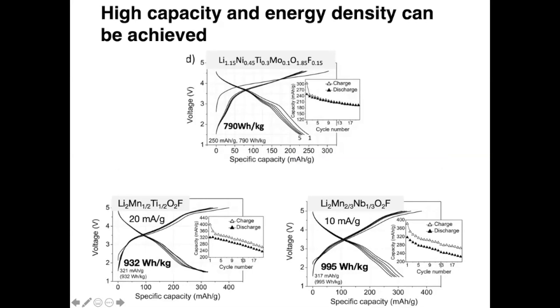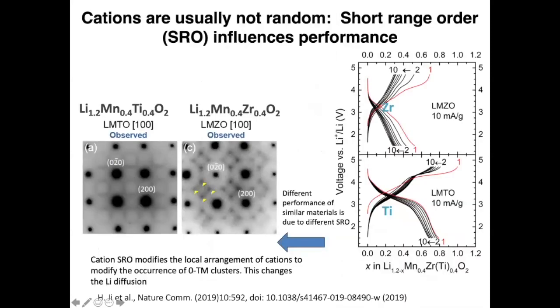You can, in general, get quite high capacity. A lot of these materials hit 700, 800, even approaching 1,000 watt hours per kilogram. And I'll go a little more in depth on some of these materials. A lot of them can be manganese redox based. Some of them are nickel redox based, but we have extensively investigated the manganese redox materials. So since the original invention of these materials, there's a few things we have found out. In the original work, we assumed the cations were randomly distributed because in X-ray diffraction, you see no superstructure peaks whatsoever. It's just the rock salt.